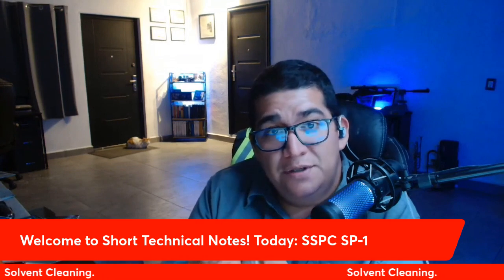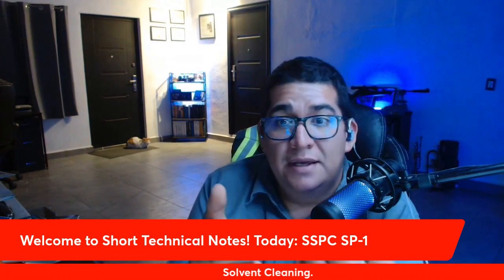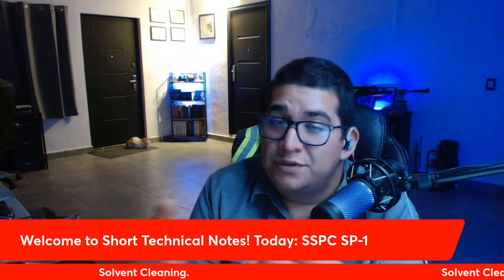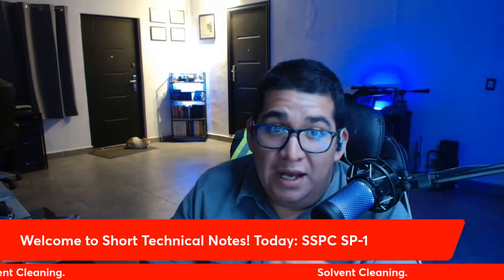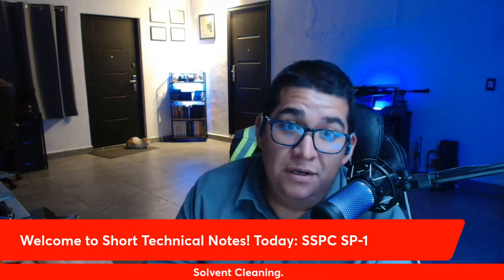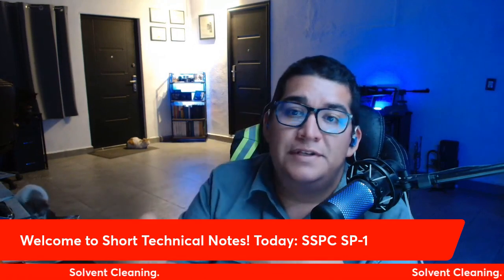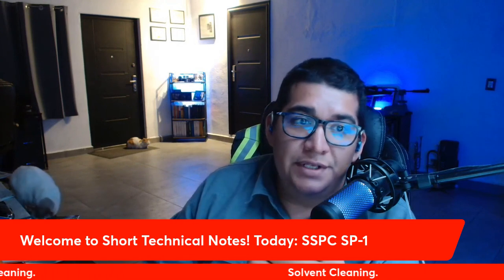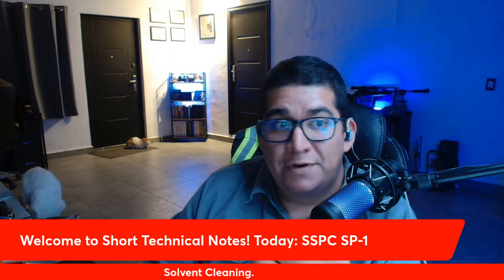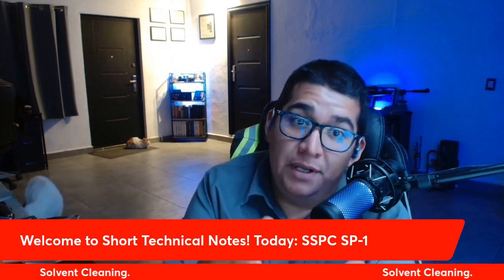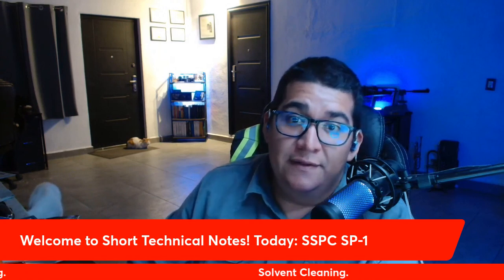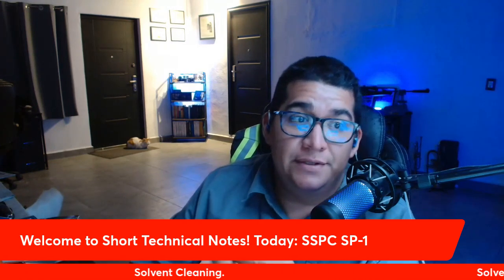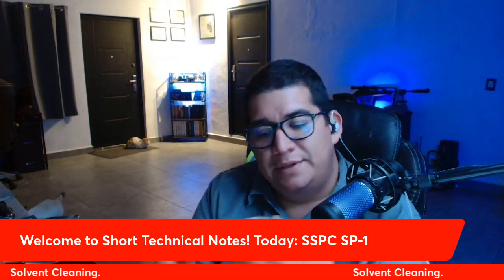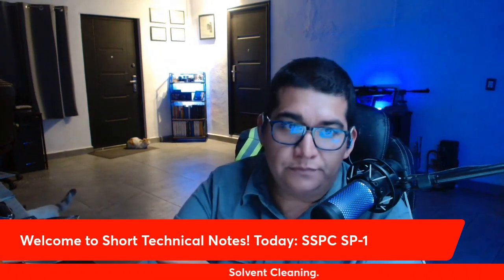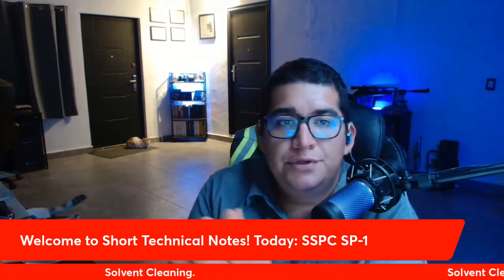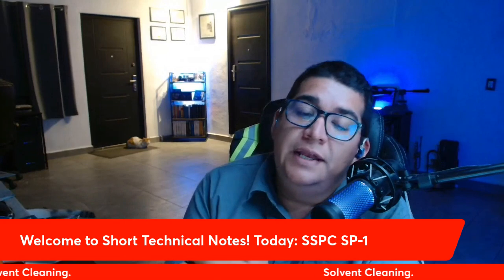About the surface preparation before and after solvent cleaning. Before solvent cleaning, there are recommendations to, for example, brush off with a stiff fiber or a wire brush in order to remove visible matter other than grease or oil. By scraping, we can remove localized deposits of oil or grease. And there are also some solvent cleaning methods. We can use a solvent and a rag or a brush to clean our material.